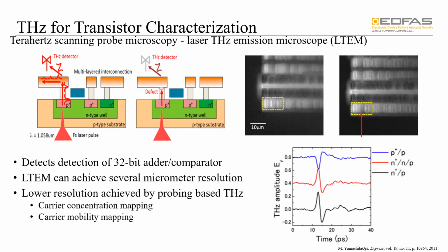Finally, we have the terahertz being used to characterize the transistor inside an IC, and this is being done by using the laser terahertz emission microscopy. This method was originally developed to analyze the defects and disconnections inside the large scale IC, and the principle of the system is described here. So we have an inputted terahertz signal from the sample backside. If there's no defects, the metal layer will then act as a terahertz antenna and generate the signals. And if there is a defect inside, there will be no emission of the signal. As you can see on the picture on the right, there is a black yellow box that shows that there's no signal being transmitted.